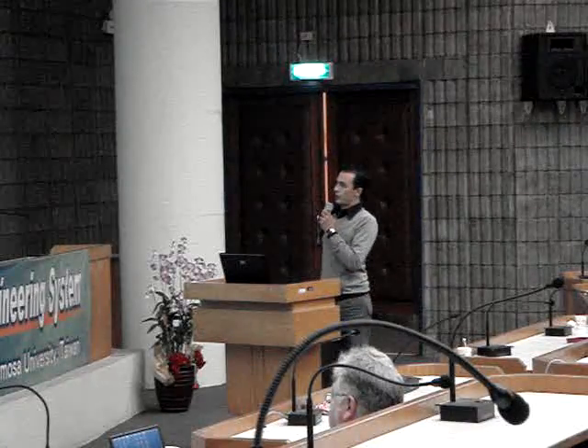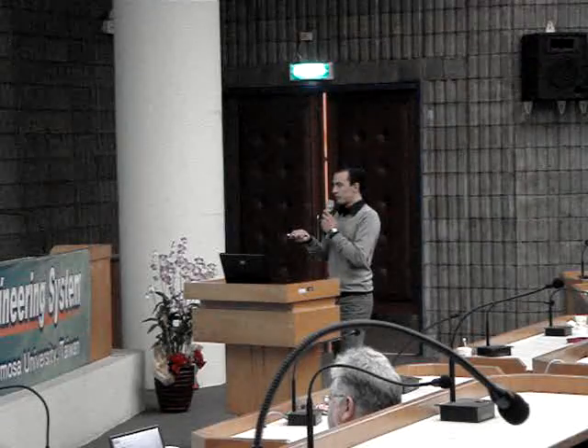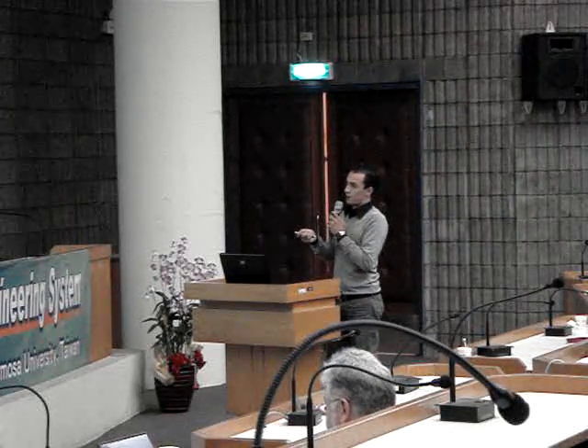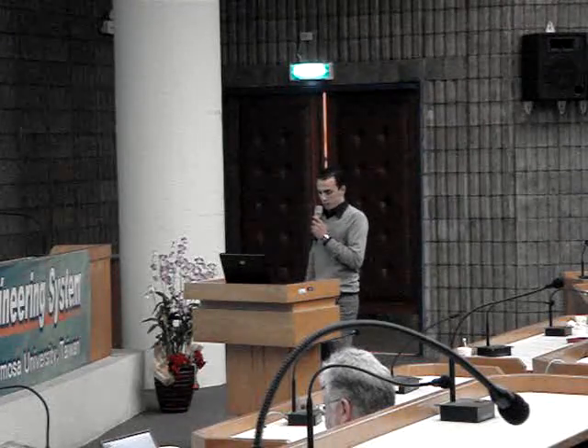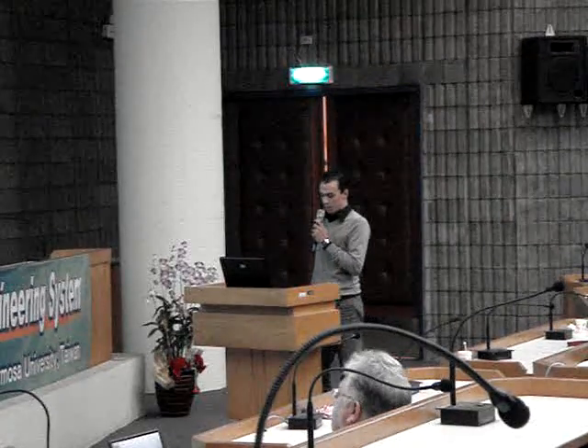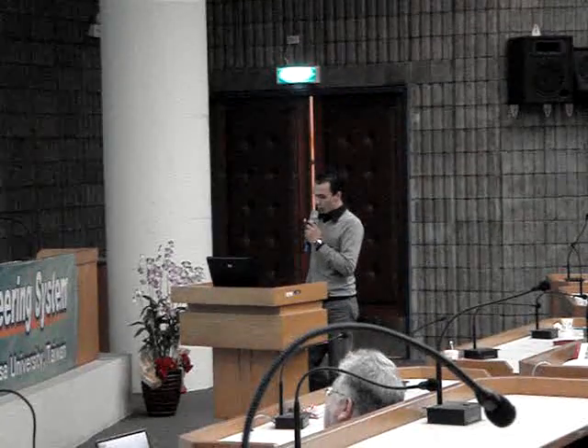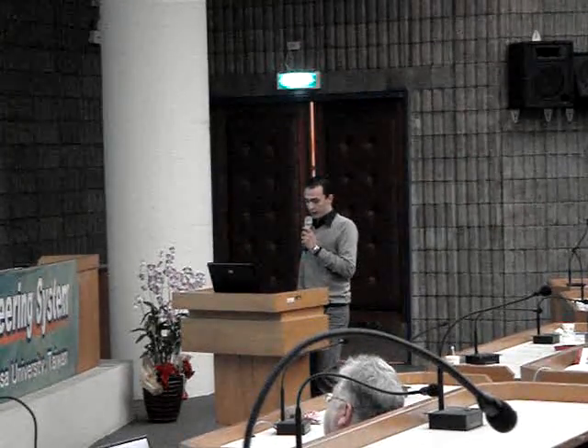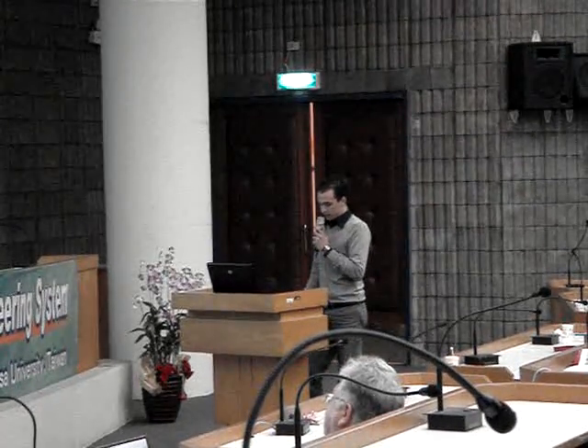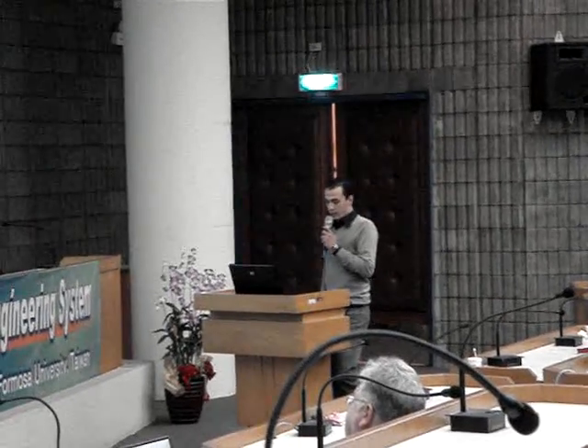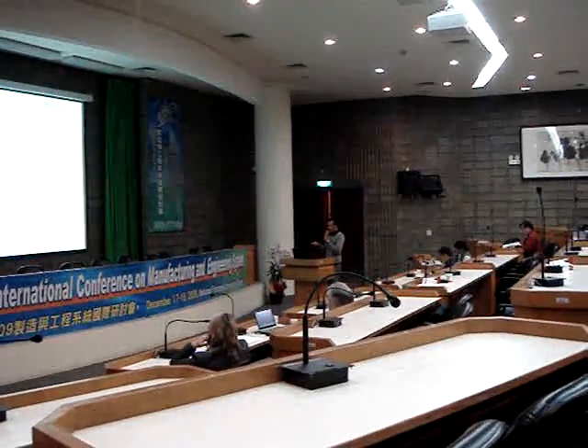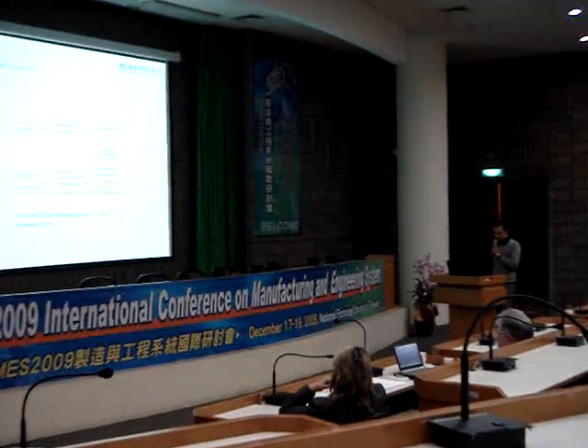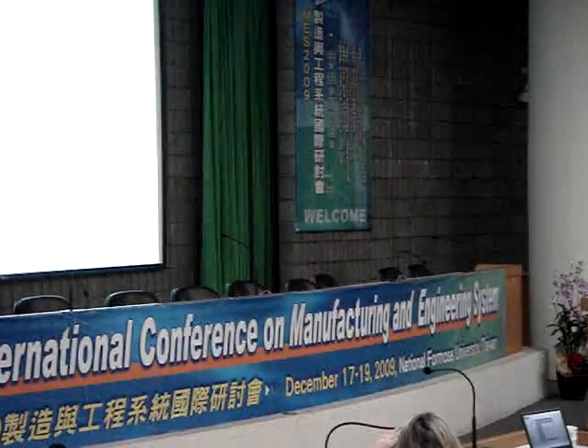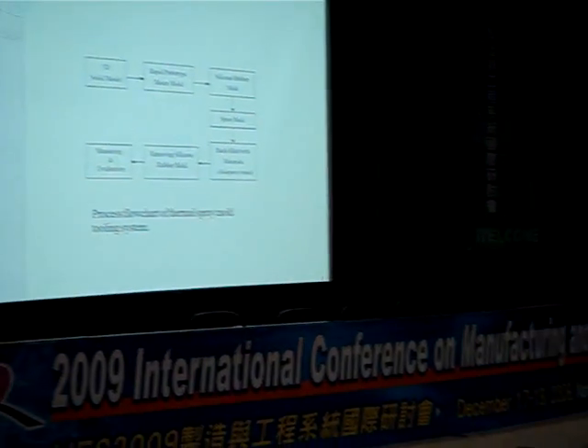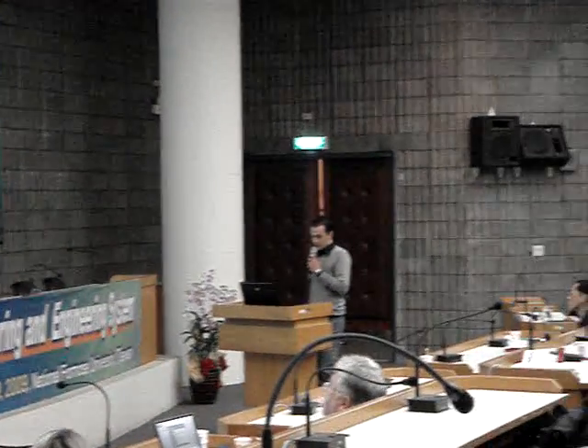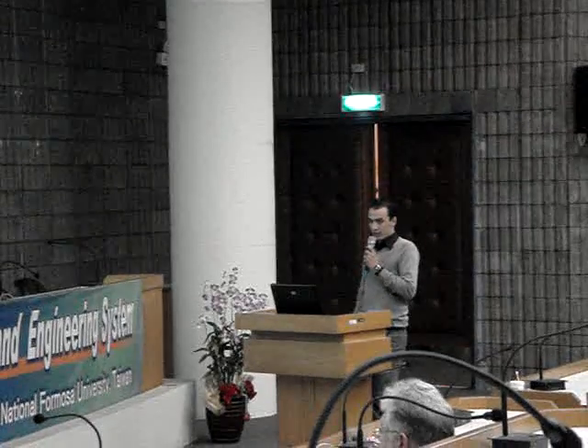Now the process shows us how the thermal spray mold tooling system works. First, we need to make the 3D solid mold. After the rapid prototyping is manufactured by the 3D rapid prototyping machine, the silicon rubber mold is made by inverting from the master pattern of the rapid prototype sample. Then we use the silicon mold as a substrate for our high pressure thermal spray system. And in the end, we use an aluminium epoxy powder mixture to make the backup of the spray layer. Finally, the spray metal shell is separated from the silicon rubber mold to obtain the desired pattern.